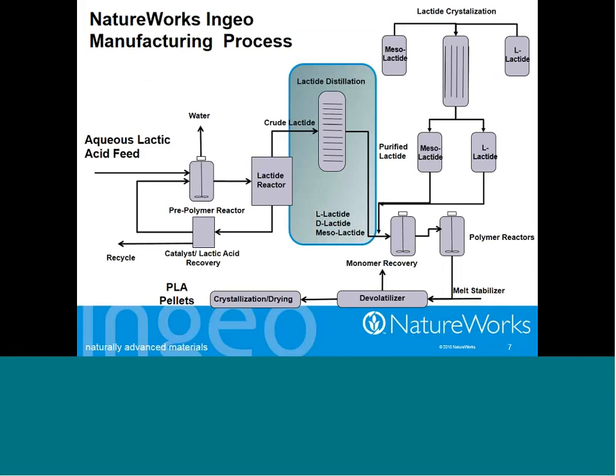The next portion of the plant is the distillation process, and that is used to accomplish 2 things. It is used to remove, as I mentioned, the lower boiling or the lower molecular weight oligomers that come out of the lactide reactor, and it's also used to set the stereoisomer composition that's fed to the polymer reactor. So the specific ratios of meso, D, and L determine the product quality or the product attributes of the PLA resin that we make. Distillation is a really efficient means to produce these lactide compositions.